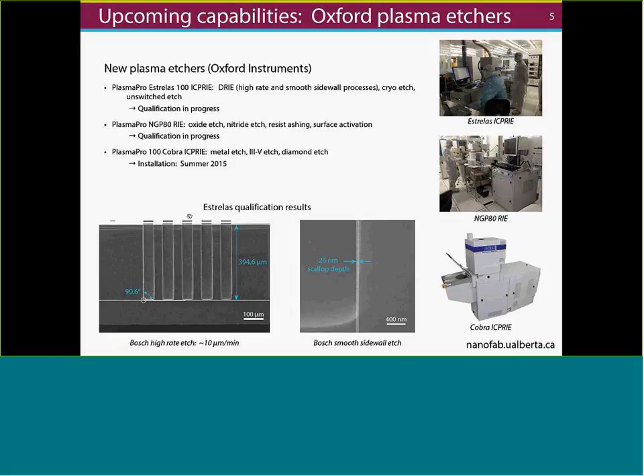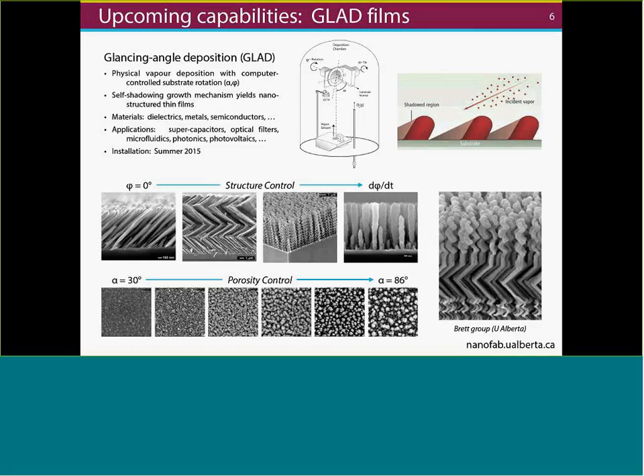Now, in addition to this sort of high-rate Bosch etch, we are also qualifying a very smooth sidewall etch where the scallop depth is only less than 30 nanometers. So in addition to the Estrelas and our RIE tool for oxide nitride etch and ashing surface activation, we're also in the next few months getting a Cobra. This is a chlorine etcher from Oxford. This will enable metal etches, III-V materials, and diamond, other more exotic materials for etching. So check back with us in a few months, and we'll have some updates on our website about these new capabilities.